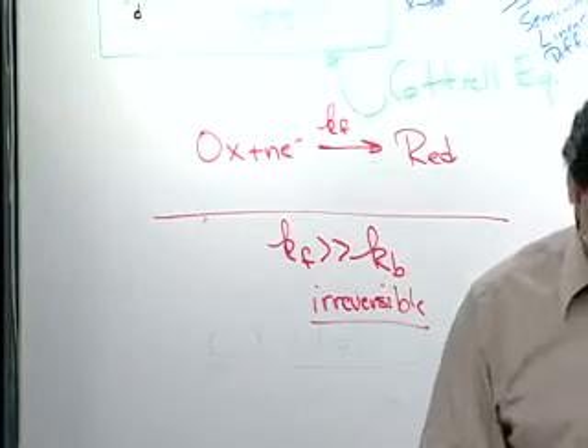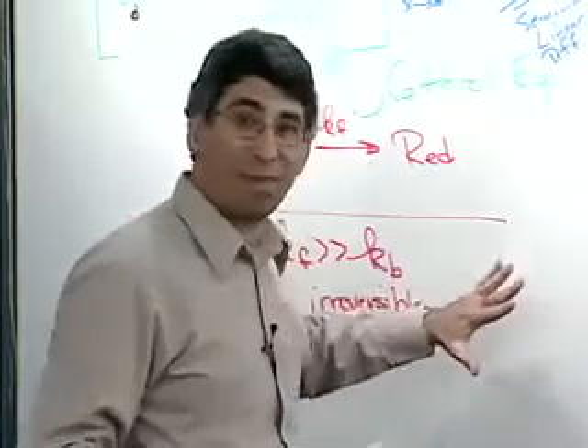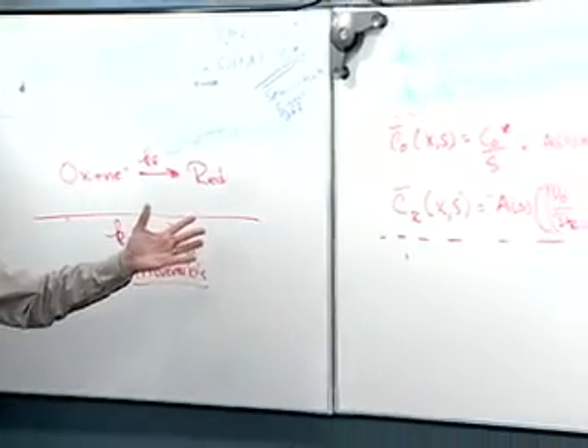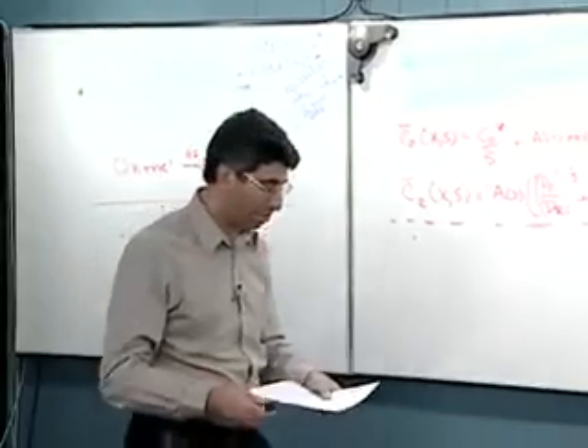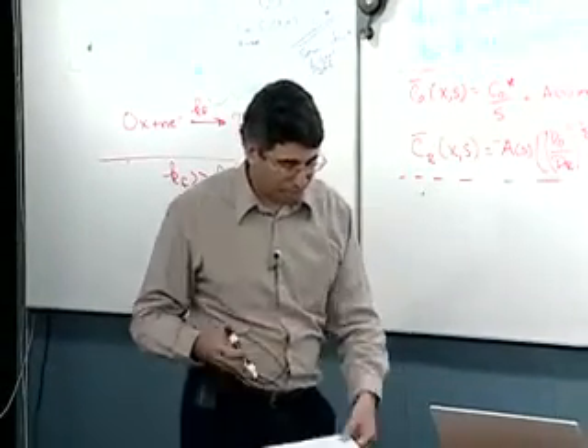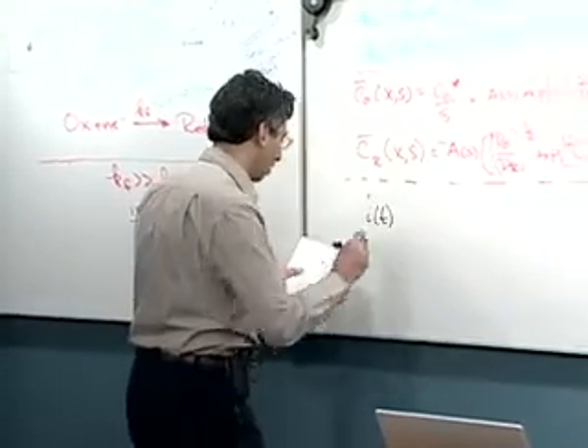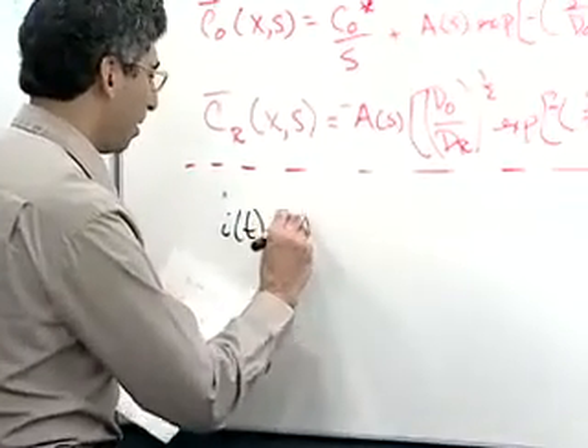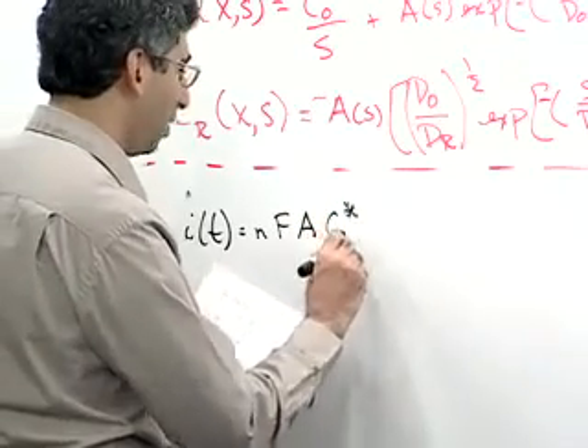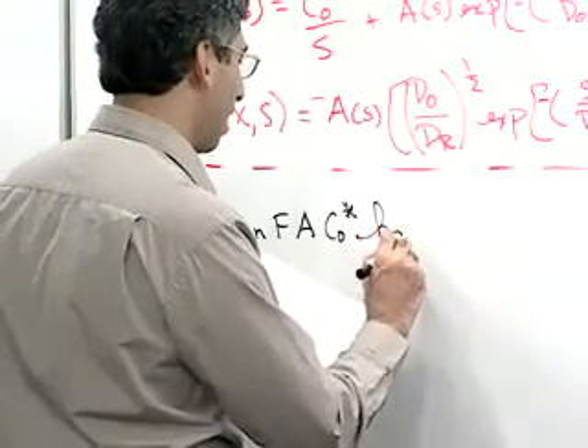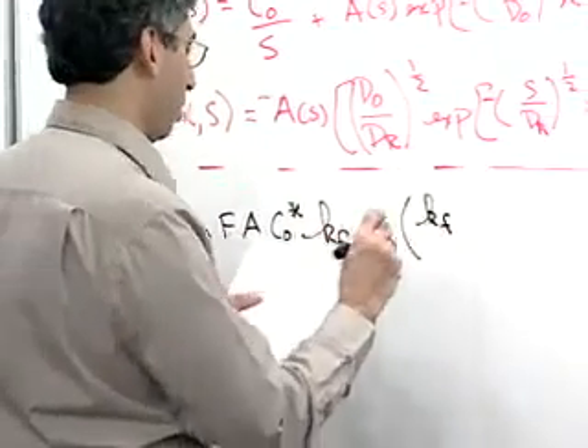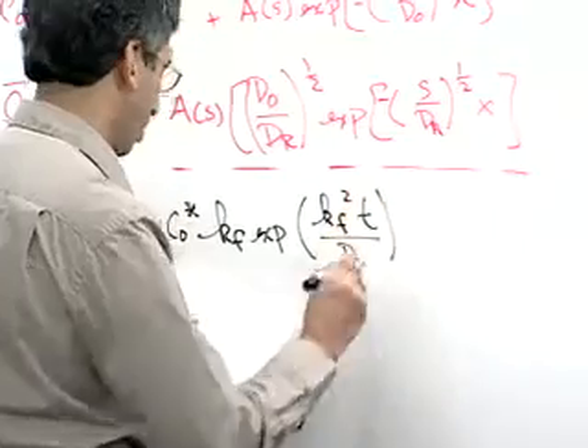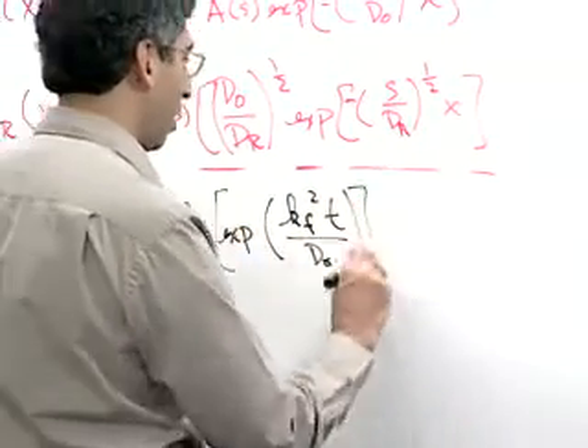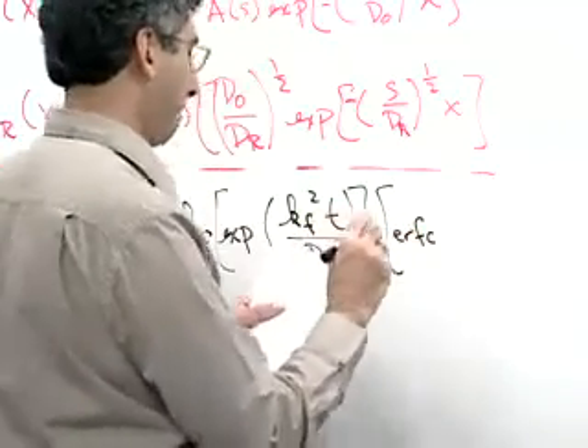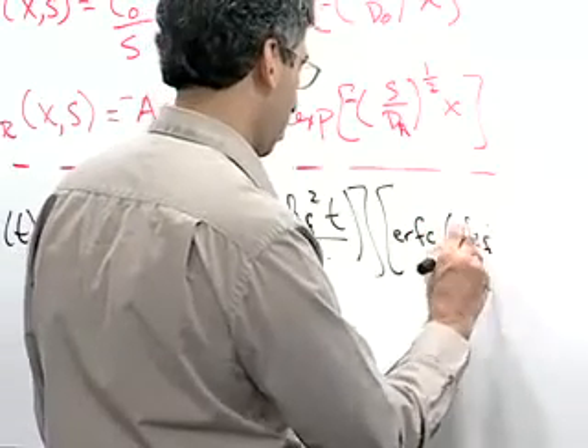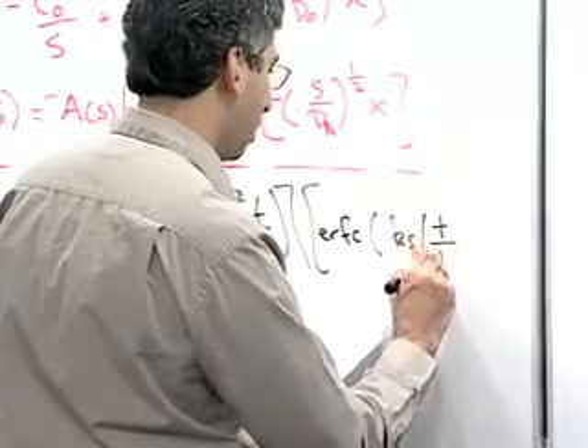And we run through the math again, start with these equations, put in our kinetic statement, which only has the concentration now dependent on k forward times the concentration, just first order in oxidized species, or I should say the current, excuse me, dependent on k forward. Then we come to the conclusion that the current, after we've done all this wonderful Laplace stuff, is equal to nFA, bulk concentration of oxidized species, forward rate constant with its hidden potential dependence, exponent of k forward squared times the time divided by the diffusion coefficient, times the error function again, of k forward times the square root of time divided by the diffusion coefficient.